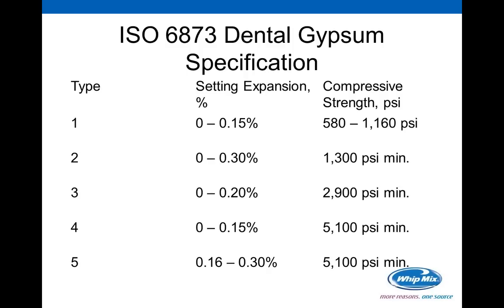Now, as we get into a type 3 stone, you can see once again that the expansion can be anywhere from 0 to 0.20. This is a percentage, and we'll talk about that in just a second. And the compressive strength must be at a minimum of 2,900 pounds per square inch. That's its minimum value. Now, as we get into type 4s and 5s, these are our die stones historically. Type 4 stone can be anywhere from 0 to 0.15% expansion with a minimum compressive of 5,100 psi. And then you'll notice in type 5 stone that that expansion is a minimum of 0.16 to 0.3, still has a minimum compressive strength of 5,100 psi.